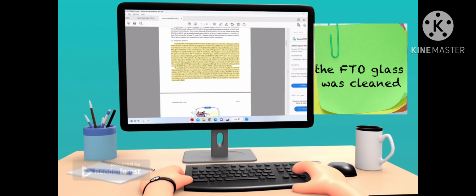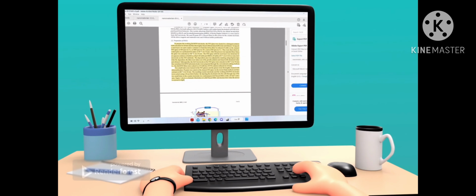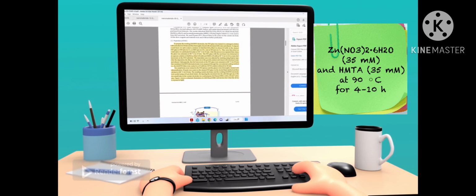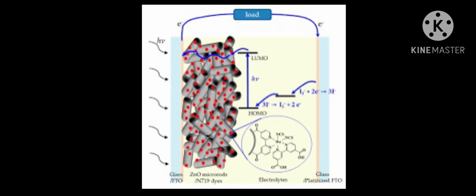The FTO glasses were cleaned with sonication for 20 minutes, then washed with deionized water and ethanol. A zinc oxide layer was deposited and dried. After this process, the glasses were annealed at 300 degrees Celsius for 15 minutes. The FTO glasses with the layer were immersed in an aqueous solution of zinc nitrate hexahydrate and hexamethylenetetramine to form zinc oxide nanorods on the FTO substrate. The zinc oxide nanorods on the FTO glasses were annealed at 400 degrees Celsius for 30 minutes.